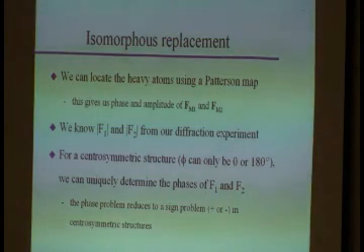And this, for example, is important for proteins because while the heavy atom has a significant contribution to the scattering, you probably have enough electron density out there that it is not the only contribution that counts, right? I mean, if I have something where the total number of electrons besides the heavy atom is less than the number of electrons of the heavy atom, then the heavy atom truly dominates the scattering.